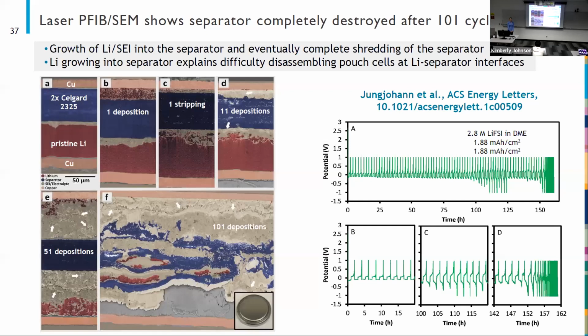Now, if we go to a high current, the performance and the images are completely different. At this high current, the cell actually failed. I'll mention this is a slightly different current and electrolyte concentration than what I use in the rest of the talk. So there's some differences here that I can go into if anyone's interested. But if we look at the upper left-hand image, we see that we've got our copper working electrode, our separator under that, our pristine lithium, this is an uncycled cell, and then our copper counter electrode current collector.